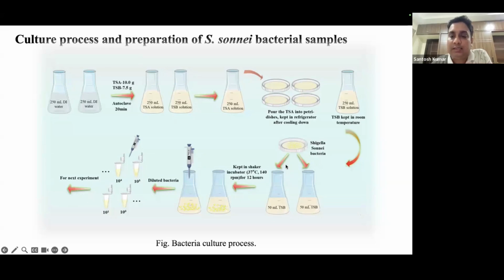Then again we need to take 50 ml of the media, and in that we need to put the Shigella sonnei bacteria, and we need to keep it for 12 hours at 37 degrees and 140 rpm in a shaker incubator, and that will help to grow the bacteria. Then we need to dilute it into several lower concentrations, and then we can go and do the detection.